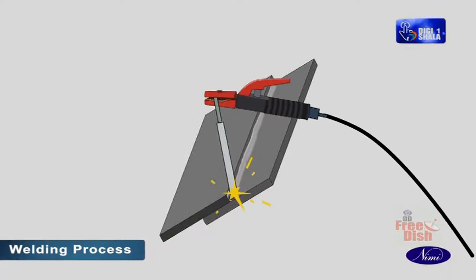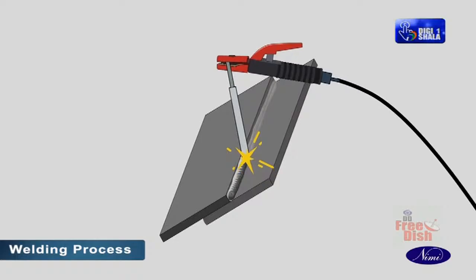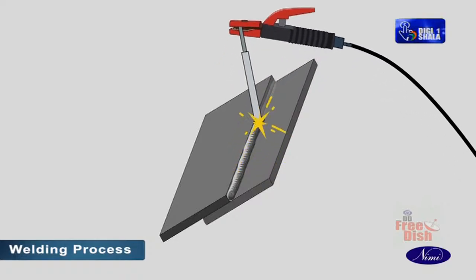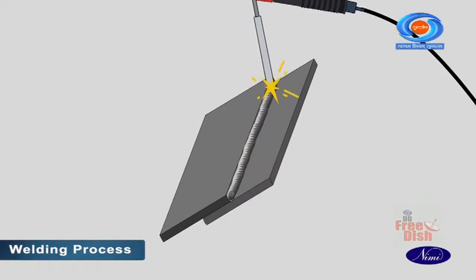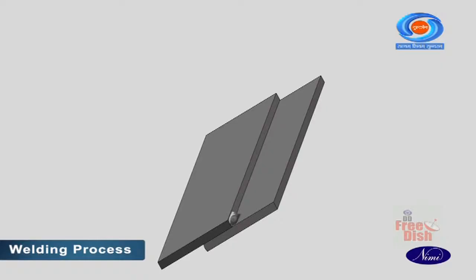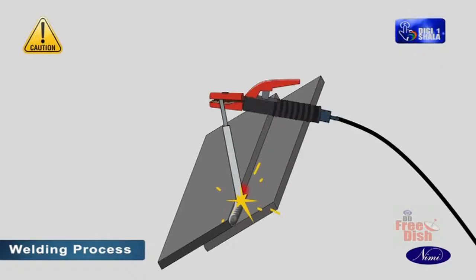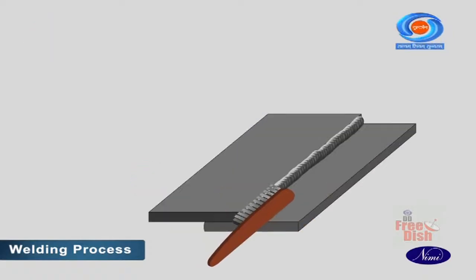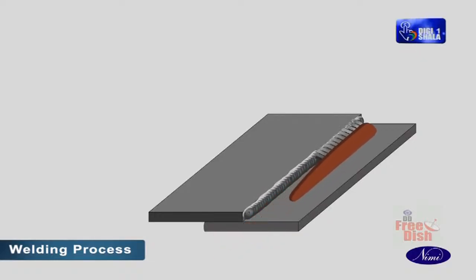Give side-to-side movement to the electrode not more than 2.5 times its dia. Prevent the upper edge of the plate from melting off by not allowing the arc to concentrate more on the upper edge. Clean the weld with a steel wire brush. Inspect the lap fillet weld for surface defects and size.